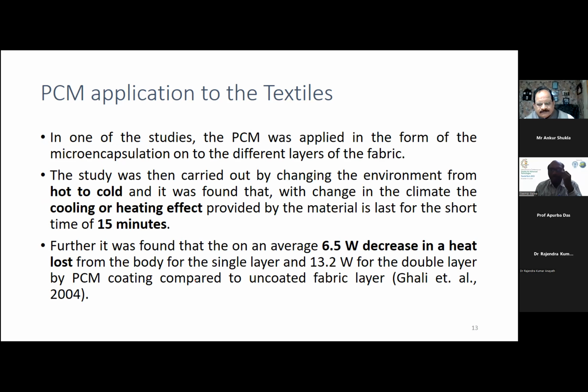So this is some of the earlier work. It was found that there was around a 6.5 watt decrease in heat loss for the body for a single layer, and 13.2 watts for the double layer, with PCM coated fabric compared with uncoated. Means there is a latent heat of up to 13 watts available in the earlier research. But in our research at present, the one which I am going to show, we received up to 40 watts, a 40 watt difference.